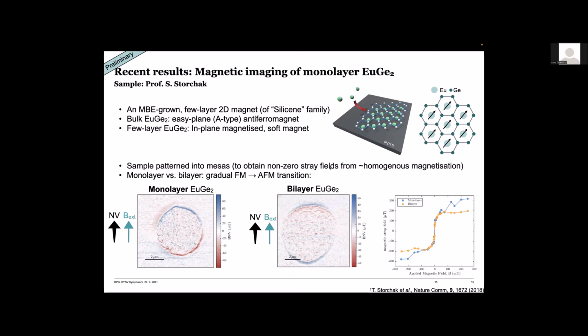So here we had to introduce some boundaries to this material in order to get stray magnetic fields out of it. And the trick we played was to introduce mesas into this surface. So we etched or patterned this two-dimensional magnet into mesas of various shapes, where then stray fields would emerge, and that would allow us to address the magnetism in this material. And here you see two such examples.